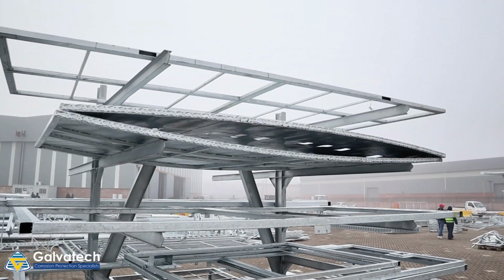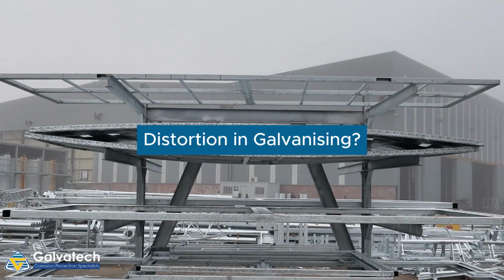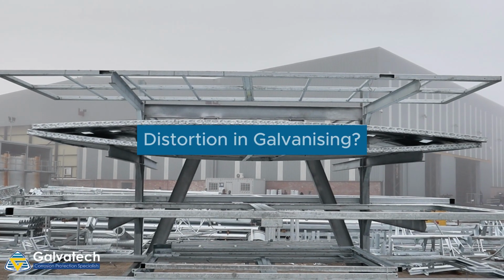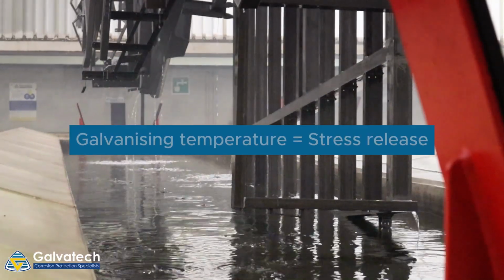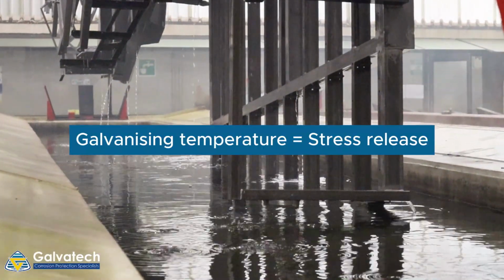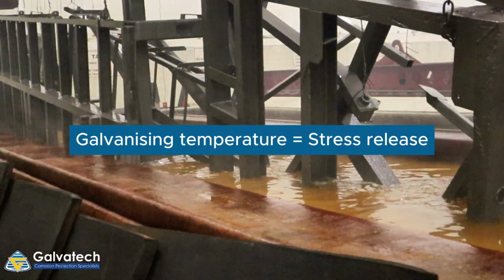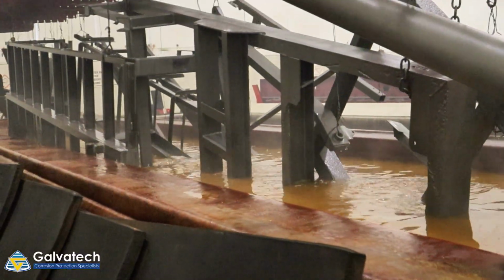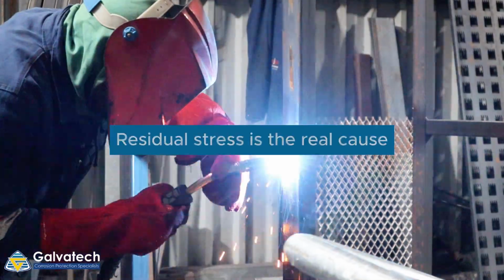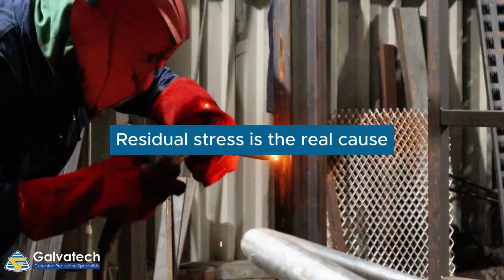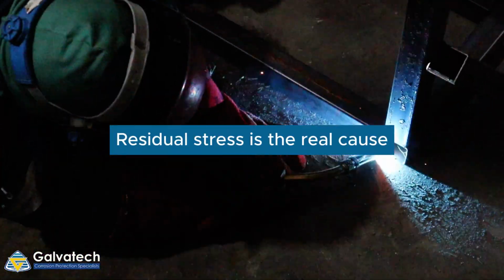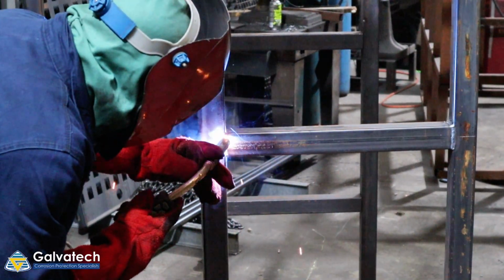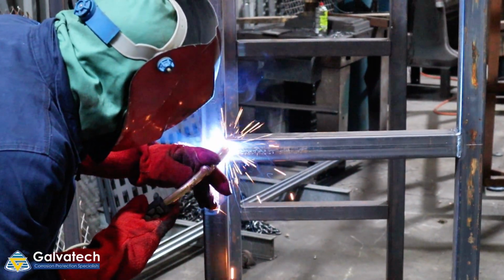Have you ever received hot-dip galvanized steel that looks slightly bent or distorted and wondered what happened? Distortion happens when steel is exposed to heat during the galvanizing process, causing internal stresses to be released. Most distortion is caused by residual stress from welding, cutting, or uneven fabrication, not the galvanizing itself.